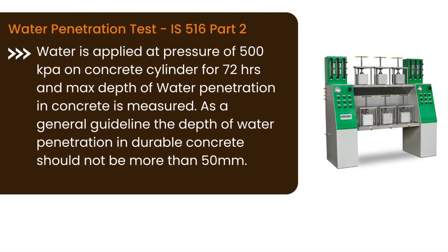Water Penetration Test IS-516 Part 2: Water is applied at a pressure of 500 kPa on a concrete cylinder for 72 hours, and the maximum depth of water penetration in concrete is measured. As a general guideline, the depth of water penetration in durable concrete should not be more than 50 millimeters.